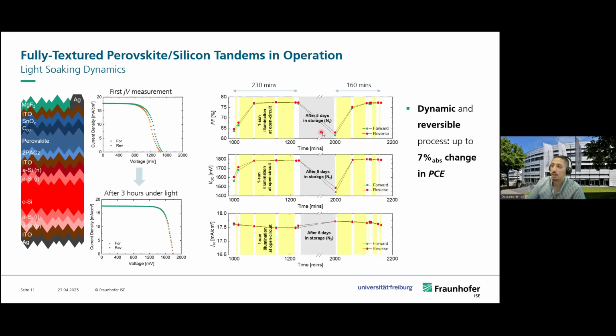And this actually was a reversible process. If we kept the cell in the dark in storage and then remeasured the cell once again, we observed that the efficiencies went down and then went up again under light illumination. And this led to around 7% absolute change in efficiency due to this light soaking phenomenon.